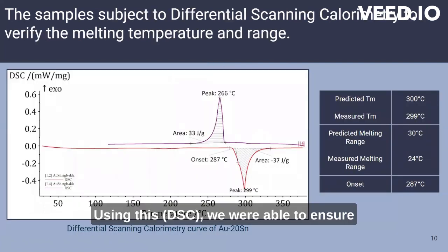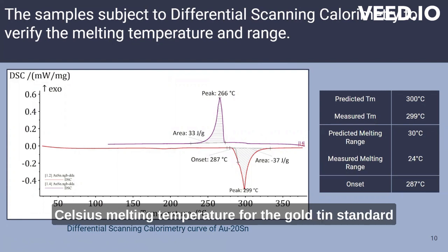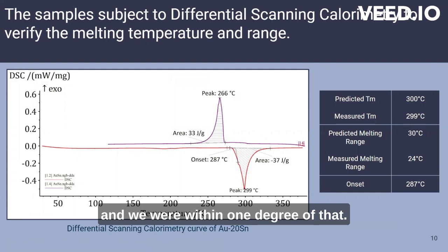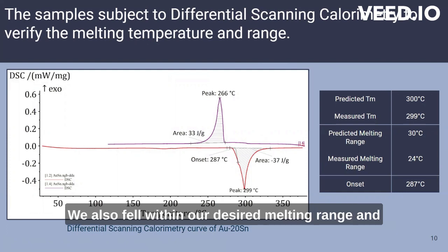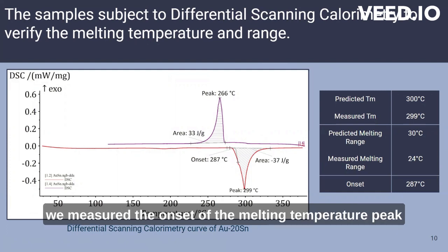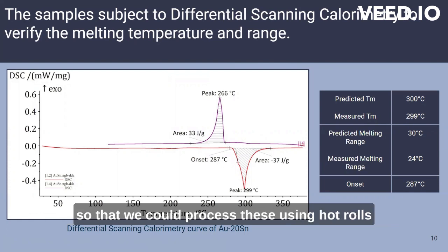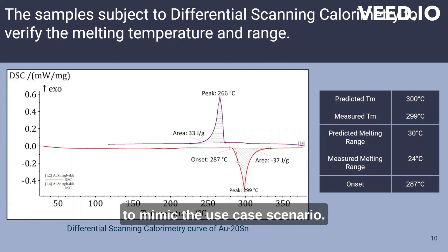Using this, we were able to ensure that we had the correct melting temperature, which was of concern to our sponsor. So here we had predicted a 300 degrees Celsius melting temperature for the gold tin standard, and we were within 1 degree of that. We also fell within our desired melting range, and we measured the onset of the melting temperature peak so that we could process these using hot rolls to mimic the use case scenario.